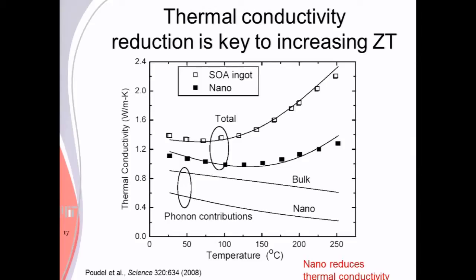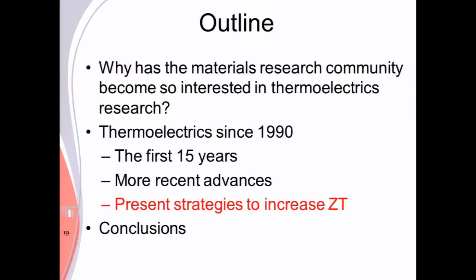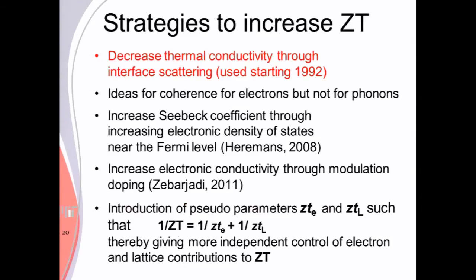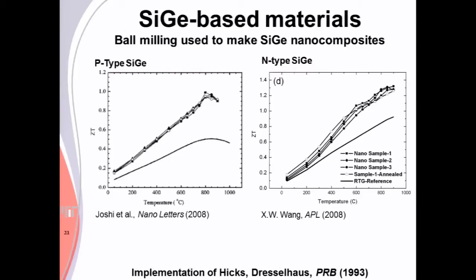And by making these composites, much of the effort and success came through control of the thermal conductivity. That turned out to be a key factor. And making a device turned out to be important. So now we come to what we've been doing in more recent times, trying to go beyond just the nanostructures. So control of interface scattering is an important thing. And people didn't believe this at the early times when we were starting this. We didn't have great public acceptance. But so this is work of Gang Chen and Zhifeng Ren.